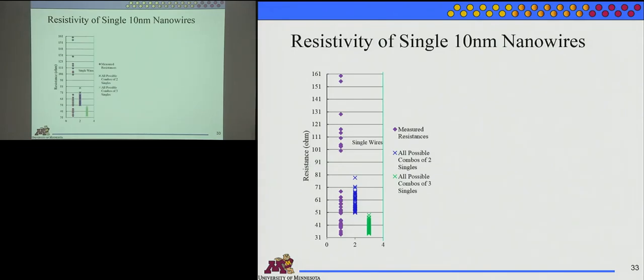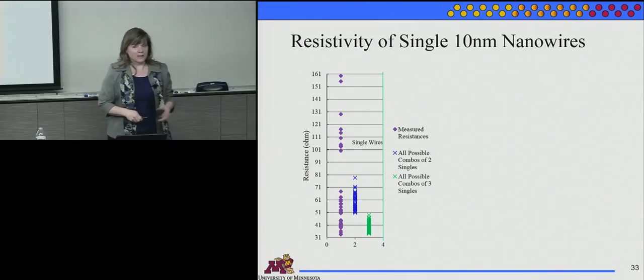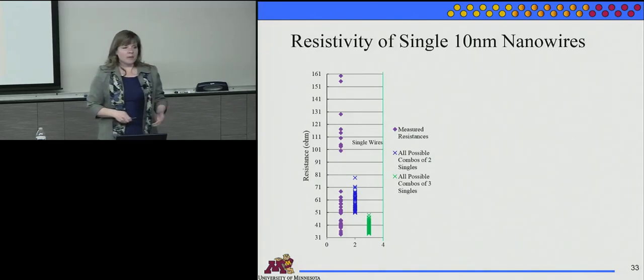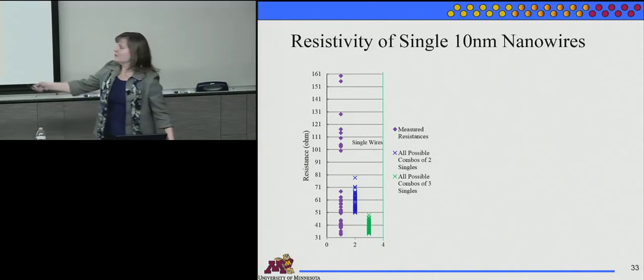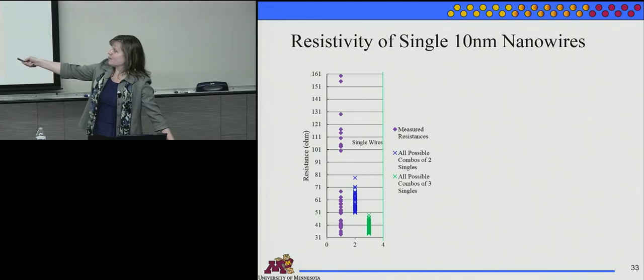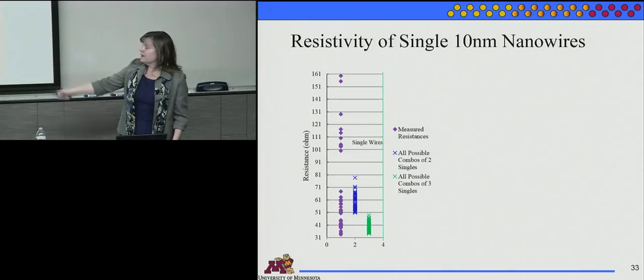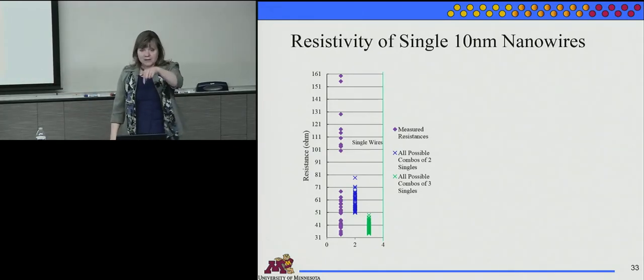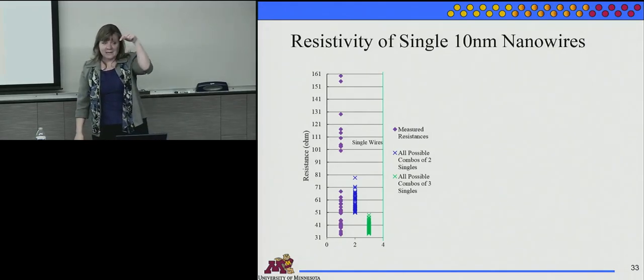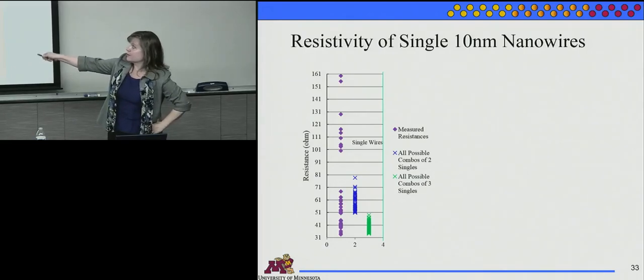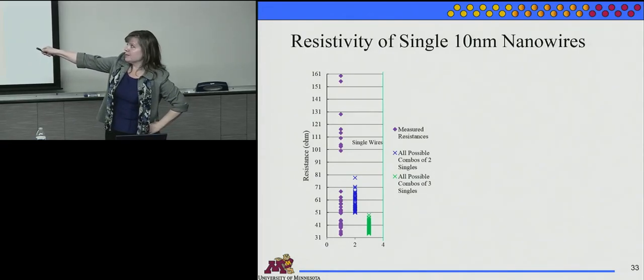And Nanoletters said, well, we don't really believe you. We want a histogram. They also wanted a reply in 2 weeks, so it took a while. And we finally ended up getting a histogram. All the purple measurements there were seen as measured, the very sharp tip coming down and measuring individual 10 nanometer diameter wires. So we said, these look like they're probably single, because maybe you'd say those could be 2 single wires and these are double.